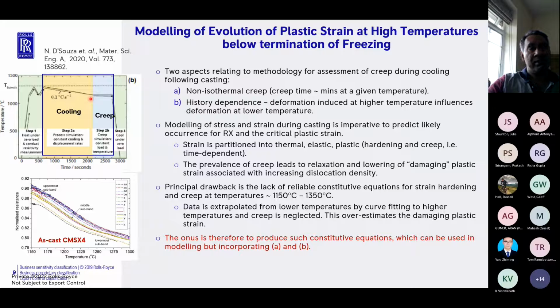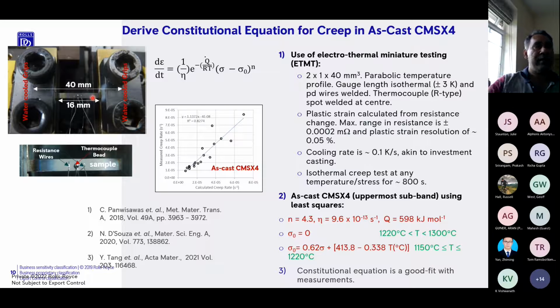In other words, at 1300, at 1280, at 1270, at 1250. Effectively what we did was a number of creep tests for a given cooling rate to cover a temperature range between 1300 and 1150, typically the kind of temperature range where creep is important, and creep is important from the point of view of recrystallization. We did this using miniature testing.